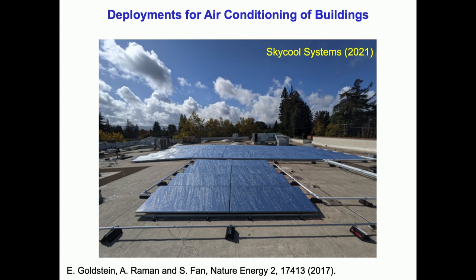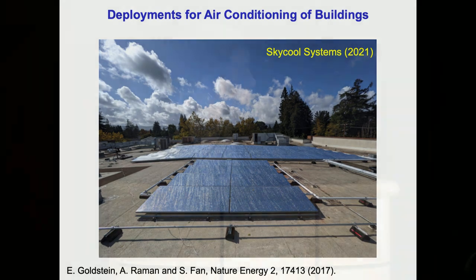Well, one of the important applications of this is for air conditioning of buildings. And in this case, what we do is we couple a radiative cooler with a standard air conditioning system. We lower, for example, the water temperature below ambient and use that to drive a water-based cooling tower. And this is slowly but steadily getting deployed in California through a startup that I co-founded with two of my former postdocs. This is now led by Dr. Eli Goldstein. And this is a picture of one of these SkyCool systems set up in some of the supermarkets around here.